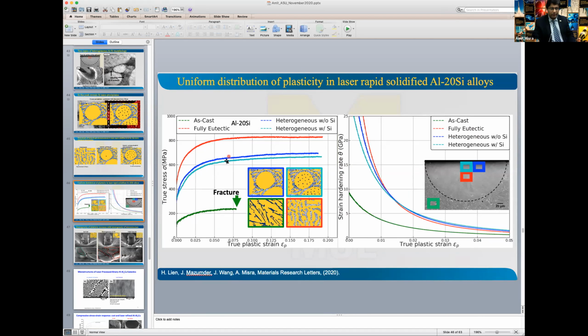Yeah, so that's a good point that we are trying to analyze in more detail to get more statistics. The initial thinking is that those silicon particles in the samples that we tested were coarse. And so we think they are not doing much in terms of precipitation hardening. And so that's within the, I would say, scatter range for doing these tests. So we have to find a way to make those silicon precipitates finer. We just don't know how, in terms of what knob to turn in the processing, because the hypothesis is that in the primary aluminum dendrite that formed, some silicon was trapped, and because silicon is not soluble, it precipitated inside.